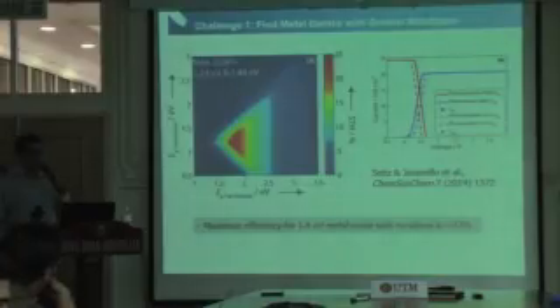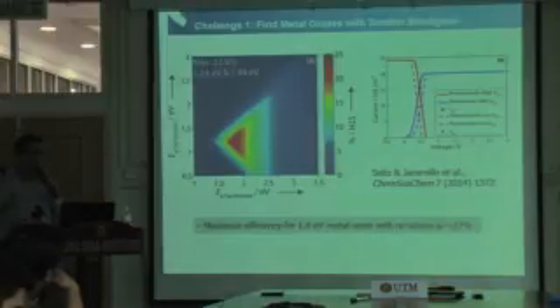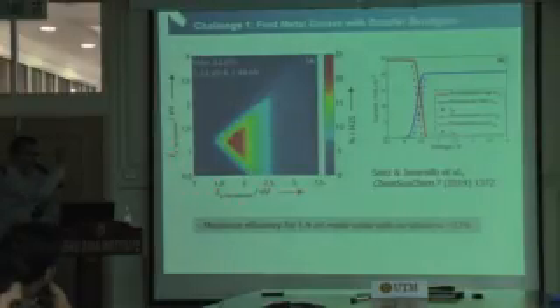So what we can do now is find metal oxides with smaller band gaps. In a way, this is really a material question. Materials researchers need to study different metal oxides, improve them, or find a new metal oxide that has a smaller band gap. So this is a calculation. A lot of people have done calculations in the field trying to predict the ideal band gap, if you think about a tandem combination or single combination. What I show over here is a tandem combination. Yeah, this is a typo. This is the top absorber, and this is the bottom absorber. So this is the large band gap part, the front part. Then this is the bottom absorber, which is the back.